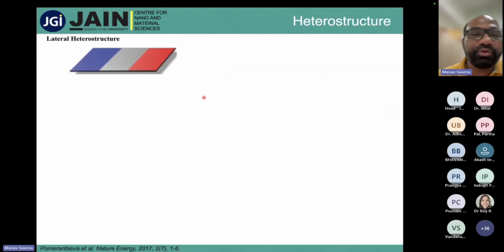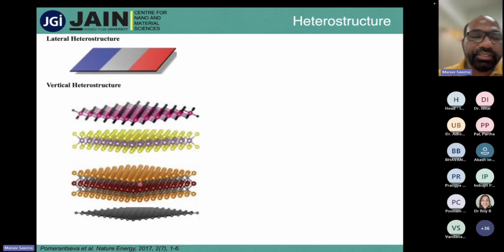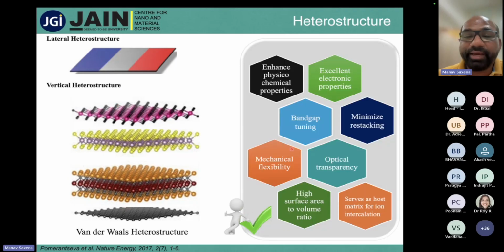Before going to the experimental part, I can show that there are different types of heterostructures, where materials A, B, C are grown in a lateral phase, whereas in other heterostructures, like a sandwich, the layers are put on top one by one, and we can make vertical heterostructures. These are also called van der Waals heterostructures, and they have exciting properties where we can tune the band gap and the optical transparency, because if a material is ultra thin, it is almost 99% transparent to optical light in the visible region. If you put one layer, two layers, three layers, you can tune the optical transparency.